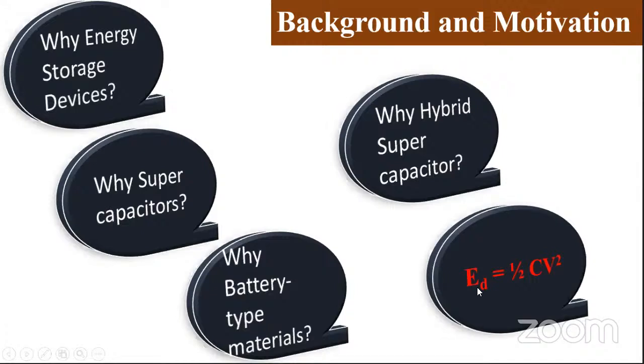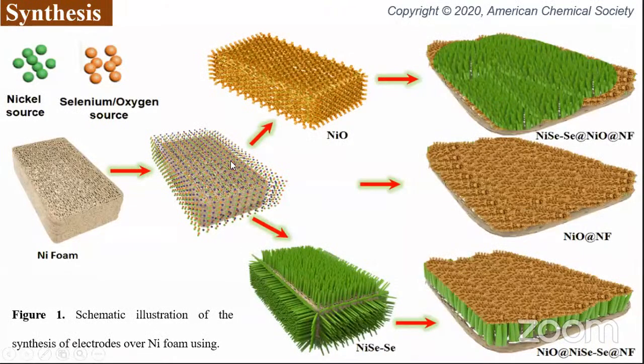Now, this equation, which is ED equals half CV squared, where ED stands for energy density, C stands for the specific capacitance, and V for the voltage window. So here you can see that ED is directly proportional to the capacitance of the material as well as the voltage window. How I've incorporated these two things into my work, I'll be discussing later. Now, coming to the synthesis part, I've synthesized three different electrodes. One, I've directly taken nickel foam as a current collector. I've synthesized nickel oxide nanoflowers over it.